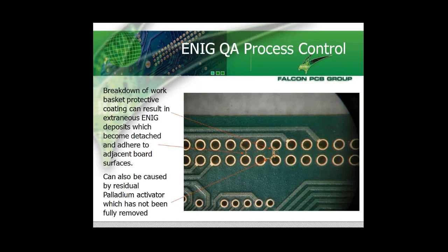Other typical potential problems that we see are breakdown of work basket protection coating can result in extraneous ENIG deposits which become detached from the baskets and tend to adhere to the adjacent board. It can also be caused, of course, in more rarer cases by residual palladium activator which has not been fully removed. But most of it does tend to come from the actual basket.